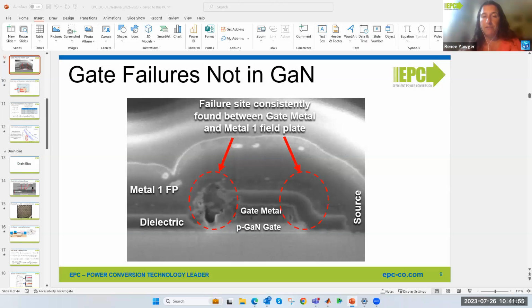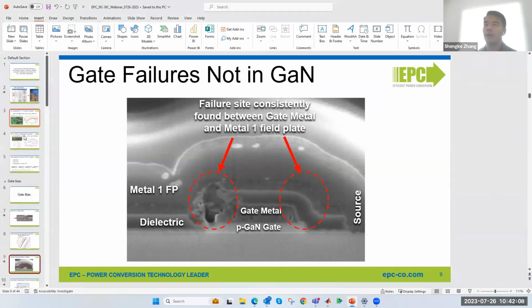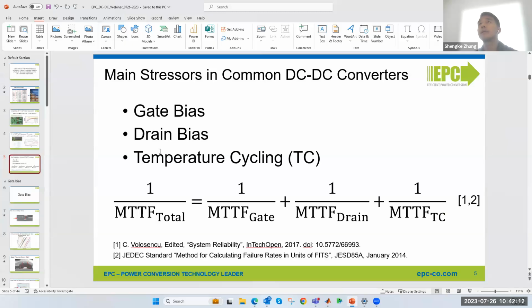Are there accelerated combined effects when both gate and drain are stressed together, or does the simple addition of MTTF, as you showed in the beginning, agree with experimental data? Yeah, I think this is okay. Let me first explain how we come up with this equation. I listed the literature on how we come to this equation, essentially based on the failure rate. When you have different failure mechanisms, the total failure rate is a simple summation of all the ones that are included, because failure rate is proportional to 1 over mean time to fail. That's how we developed this equation based on literature.